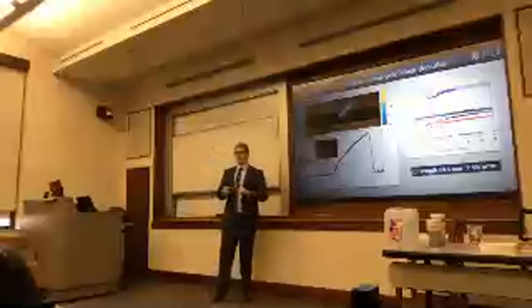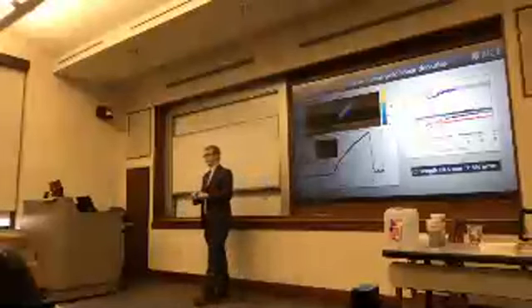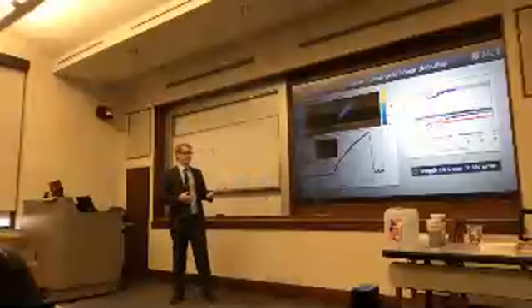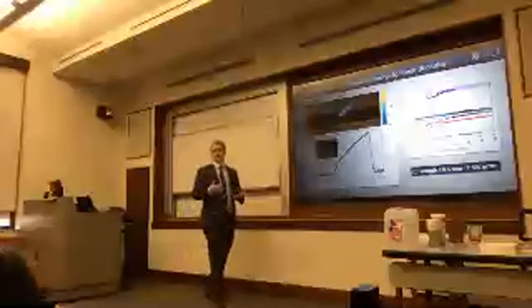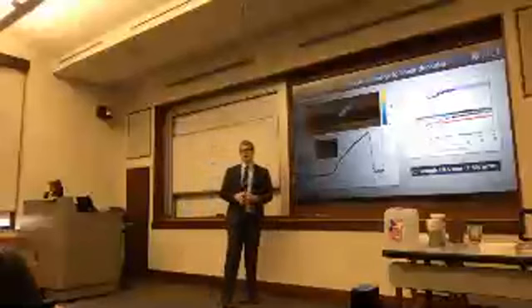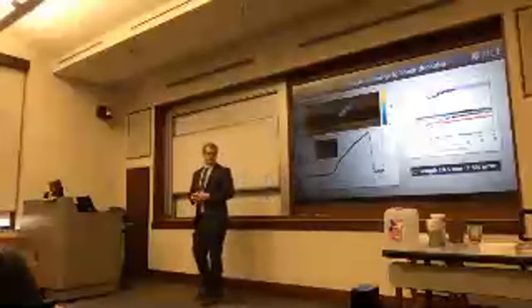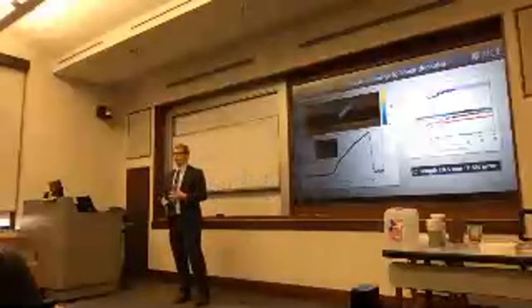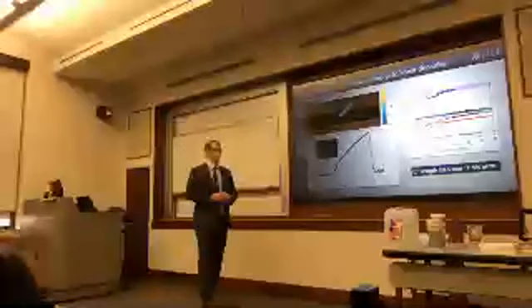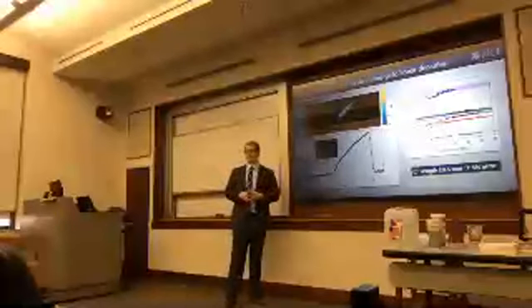Additionally, the tension is quite slow. The experiment where we're pulling on it is done really slowly. And I'm worried that the fiber could slip a little bit, or there could be some creep in the fiber that's going to also add some errors to the measurements. So we're working on improving our experimental setup to try to accommodate and take each of these factors into account so we can remove this error.